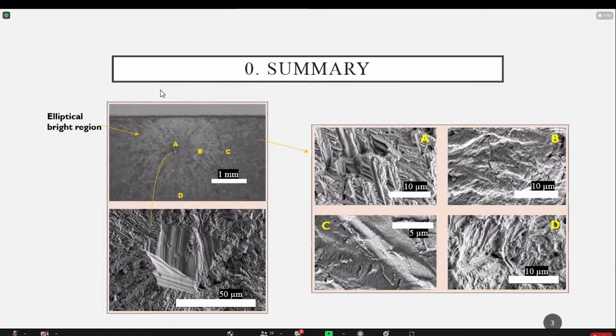The first thing you see when you look at these fracture surfaces is a very bright region with an elliptical shape very close to the specimen surface. You can see it in the upper left-hand side of this slide. Inside this bright region, there's a particularly large defect, which you can see at the bottom of that previous figure.